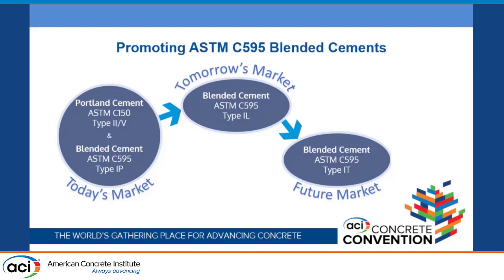Sure. I've enjoyed looking at what you're doing as far as trying to lower clinker. I was just curious, are you also increasing volume capacity at the same time? You would think you would. If you're replacing clinker with limestone, you would automatically have 10% more output at the plant. What we find is you have more time in the mill. So the same clinker going into the mill with the extra limestone, you're having to grind it finer to keep that same early strength, and it's a wash, or if not less production, making 1L compared to Type 1/2.